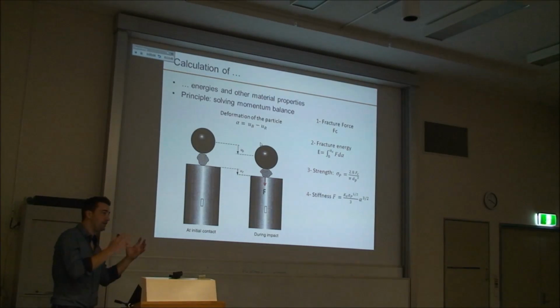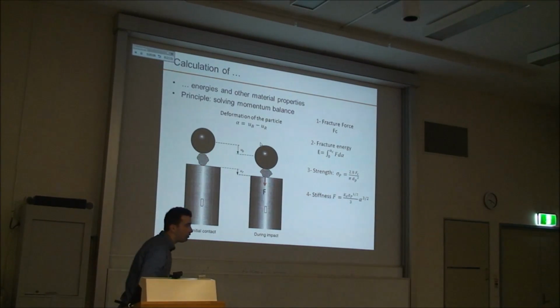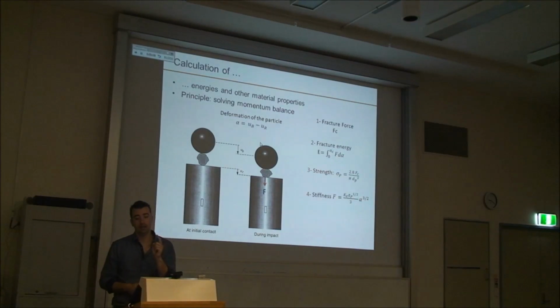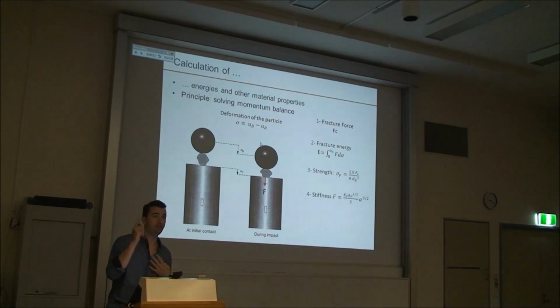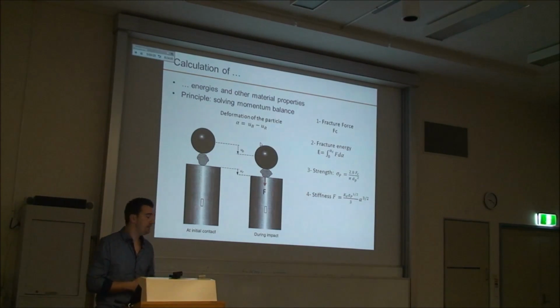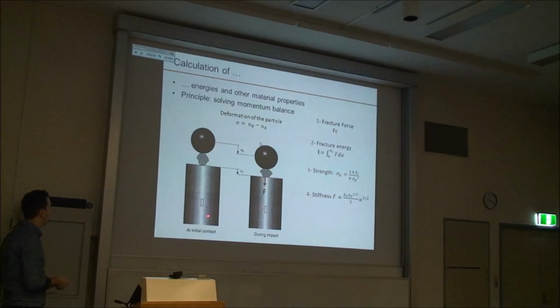So, okay, we've done one test, we've broken one particle. We have actually more than one piece of information. There's a total of 4 parameters that can be derived from one breakage, even of one particle. And this is by doing a momentum balance around the particle. So here you see the particle at initial contact and during impact. The ball is moving down, the rod is moving down, and the particle is being compressed. The deformation of the particle, or the strain applied on the particle, is actually the difference between the movement of the ball and the movement of the bar.